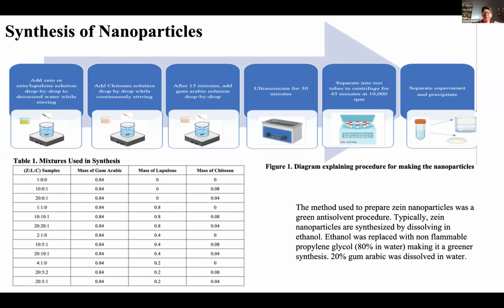Then our solutions were separated into smaller test tubes that would fit into the centrifuge, which we would use to centrifuge for 45 minutes at 10,000 RPM. After they're done centrifuging, you'd separate the liquid from the solid, save the liquid supernatant to run further tests on, and then scrape out the nanoparticles which were at the bottom of the test tube, and then weigh and dry them.